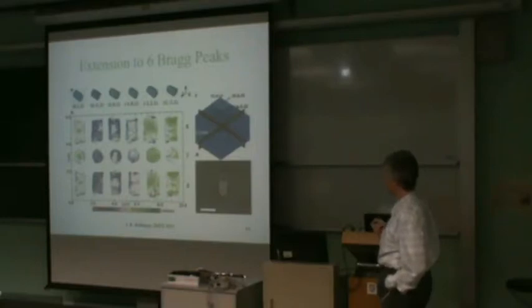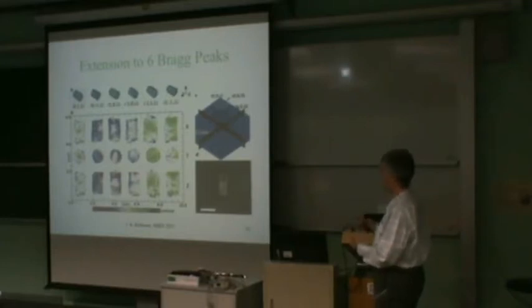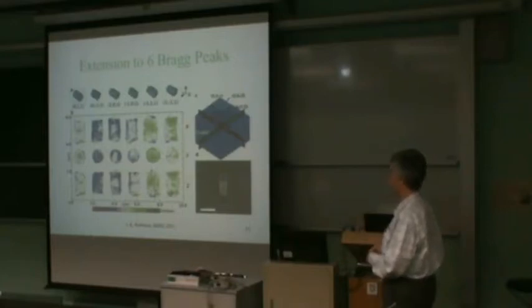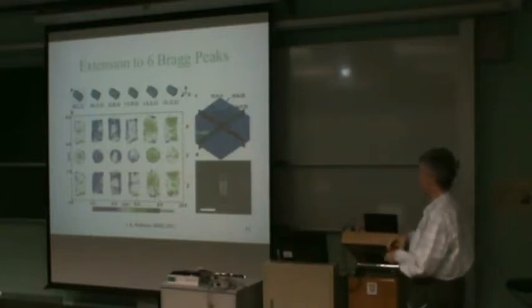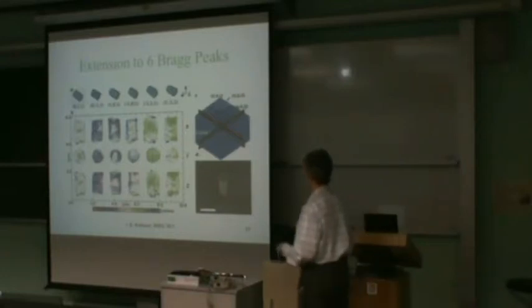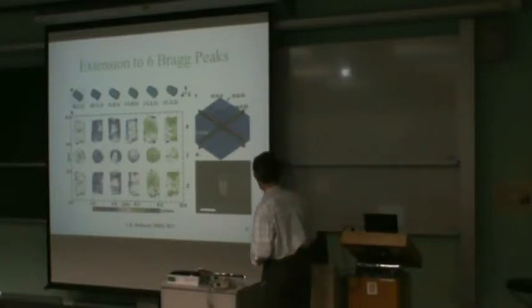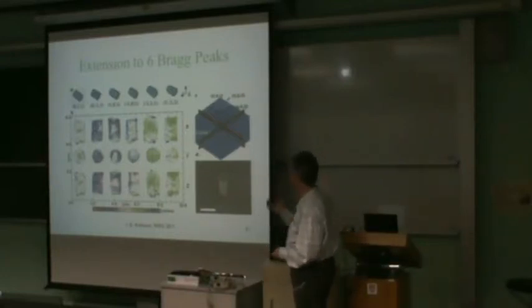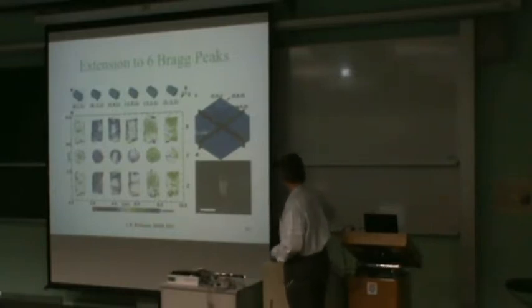And what Marcus was able to do then is to combine all of these together, because we've now got six different projections of the displacement field, which is a 3-dimensional vector. So we did a least squares fit on every pixel to the displacement field, and so he was able to get a 3-dimensional image of the displacement field mapped out inside this micron-sized zinc oxide nanowire.